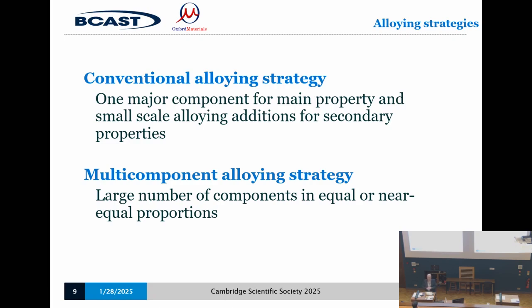That's quite useful. But to make window glass, you add a little bit of sodium oxide to lower the melting point, because it makes it easier to handle the manufacture. And you add a little bit of calcium oxide, a few percent of these things, of lime, calcium oxide, to stop it devitrifying when you use it. So those are two completely different examples where you've got a main component and two or three addition elements. So that's what conventional alloying strategy is.